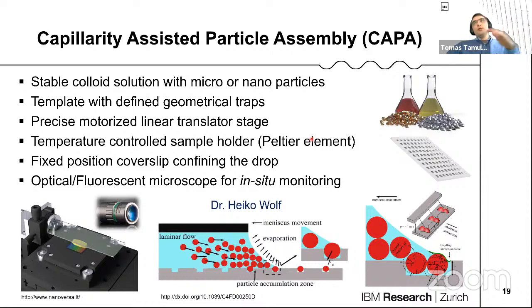You need to have a translation stage that can ensure slow translation. You need to control the temperature. You need to have some cover slip confining your drop. And it's good to have a microscope so you can investigate the process. So what happens? The liquid dries out, it evaporates, and those particles are trapped by the capillary force in the obstacles that you have designed in your template. In such a way, you can cover big areas with nanoparticles with 100% yield.